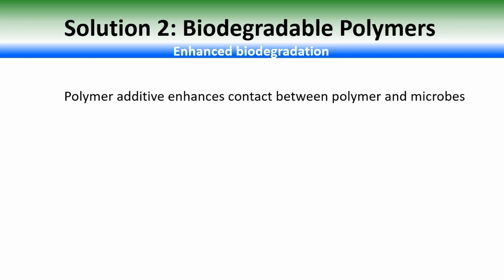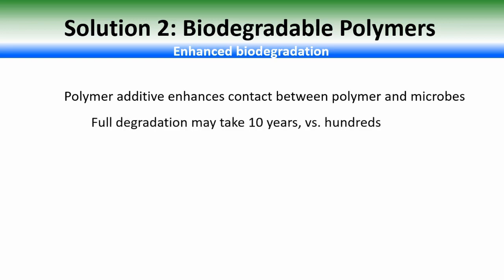Recently, a new technology has been introduced that seems to fit in between truly biodegradable materials and those that are typically considered not biodegradable. This technology involves the use of a polymer additive that enhances access to the polymer by microbes, thereby speeding up the otherwise very lengthy natural degradation process. Initial tests indicate that full degradation using this additive may take about 10 years, which is clearly much slower than accepted definitions of biodegradability, but it's still a significant improvement over a timeline of several centuries.